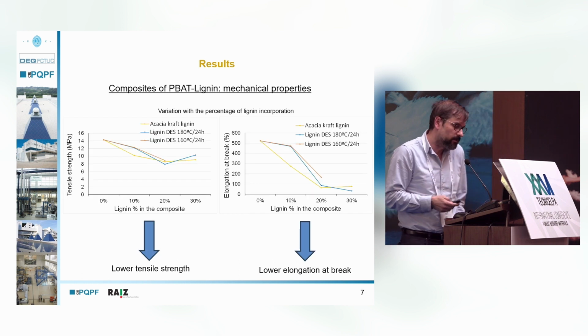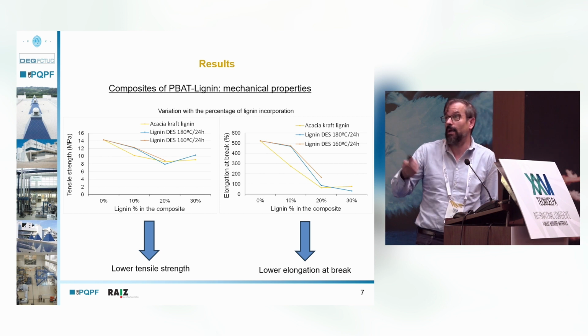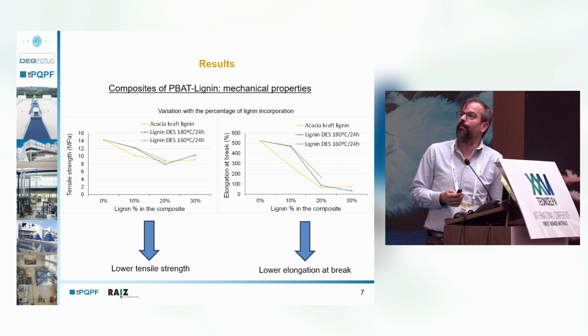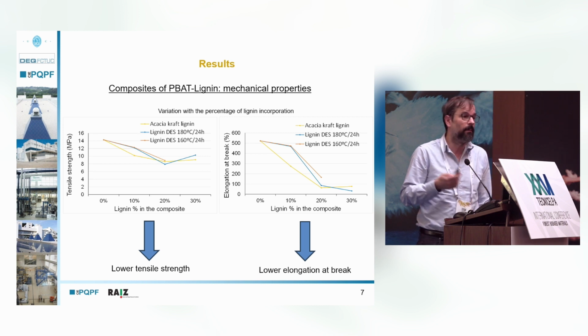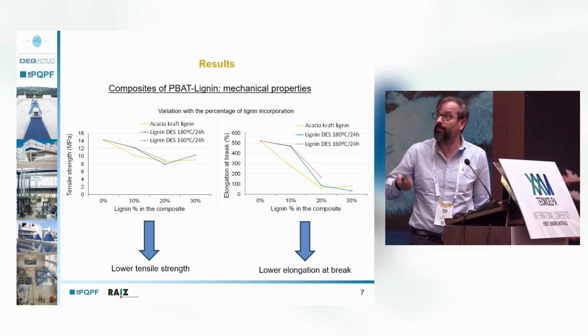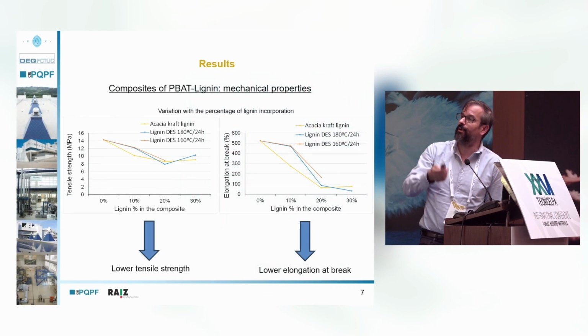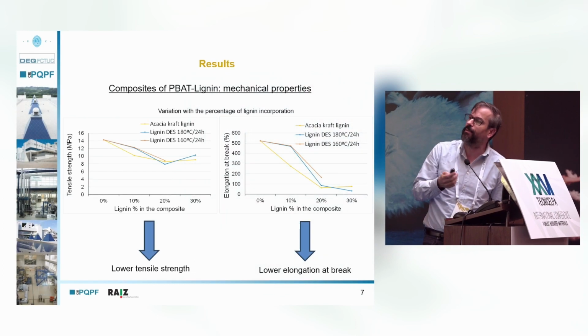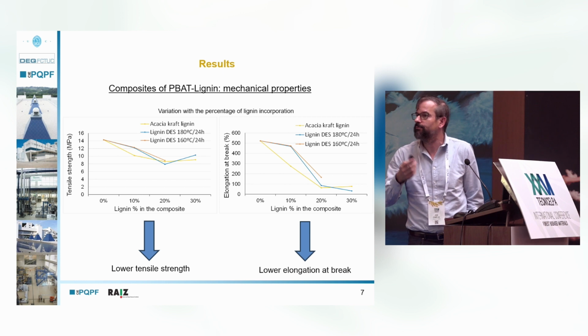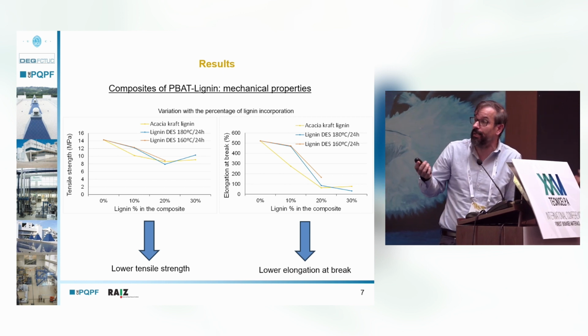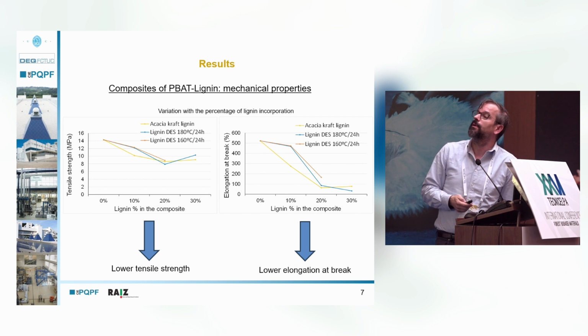The most important part of this presentation, I think, is the results for the composites of PBAT lignin. I just show, once again, only the mechanical properties. There are other data, but I don't have time to show these results here. As for the mechanical properties, we can see the variation of tensile strength and the elongation at break with lignin percentage in the composite, from 0 without lignin, only PBAT, up to 30% of lignin.